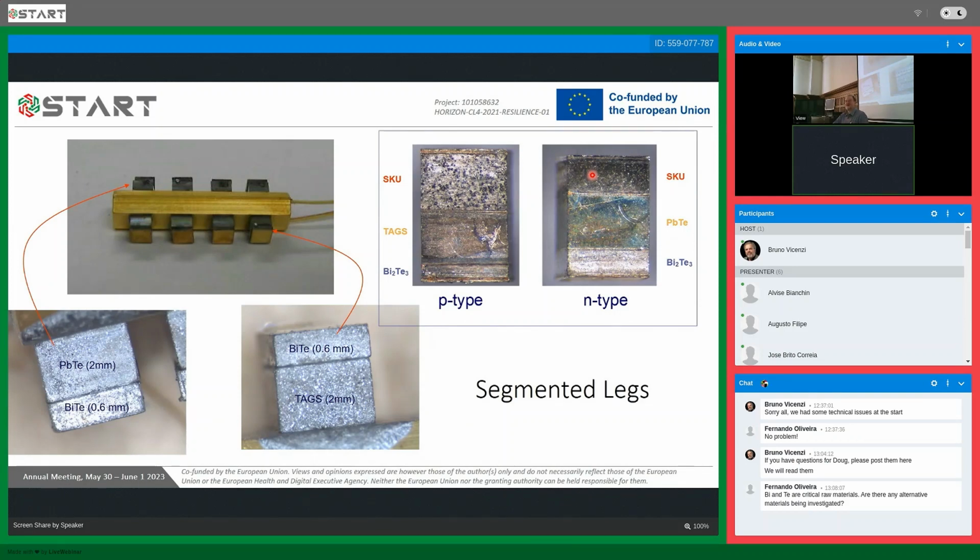Tetrahedrite, which we're talking about here as part of this program, is another material that uses copper, antimony and sulfur. And magnesium silicide, I also mentioned before. So there are silicon germanium and many other materials. They all have their niche. They perform best over different temperature ranges, which is yet another issue and challenge in thermoelectric waste heat recovery.